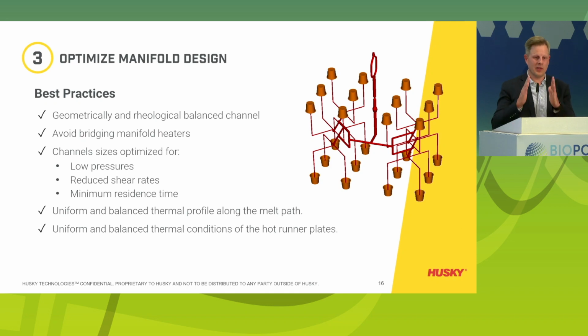We recommend to keep them individual with two thermocouples so that you can have an individual thermal interaction in case you need. And important, like I said before, uniform and balanced thermal profile all along from the inlet to the outlet to the cavity, so that we ensure there's no specific overshoot or undershoot in the system which can damage the material. And the last important point is, when you buy a manifold system, so without hot runner plates, the cooling is in the hand of the mold maker.